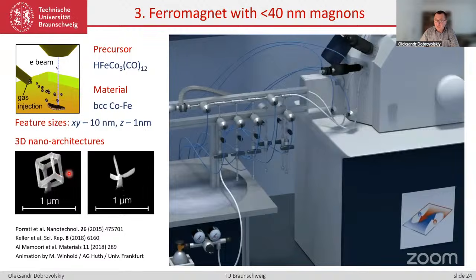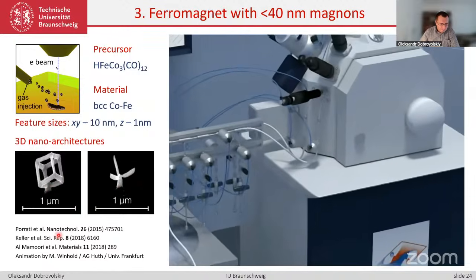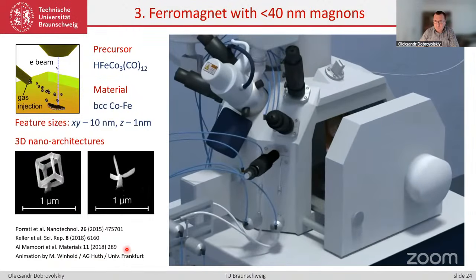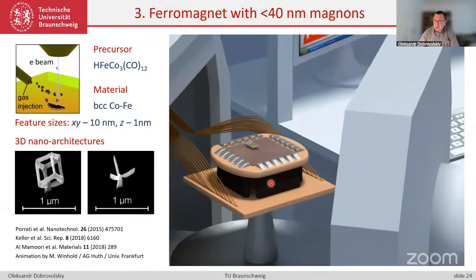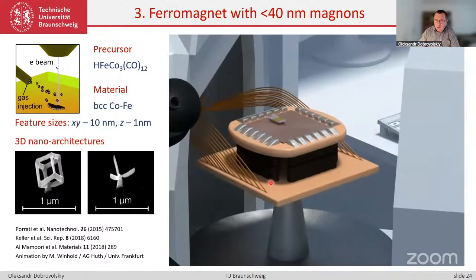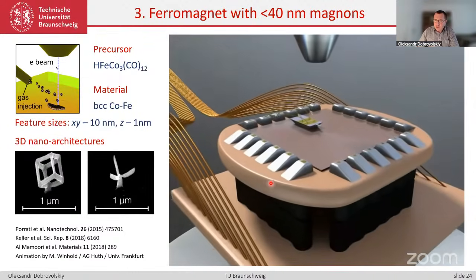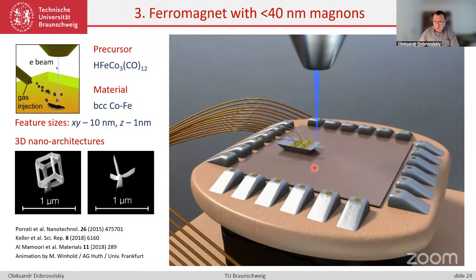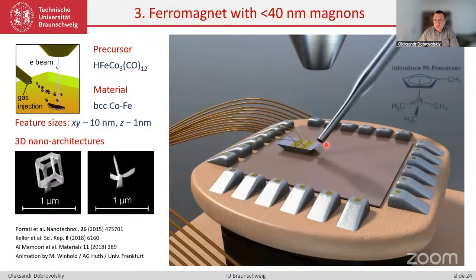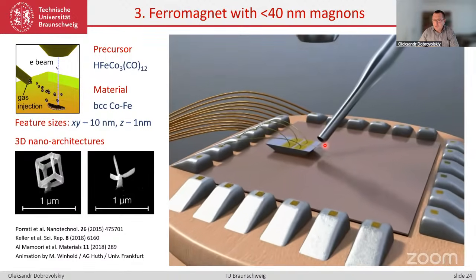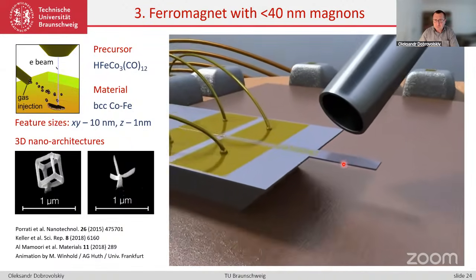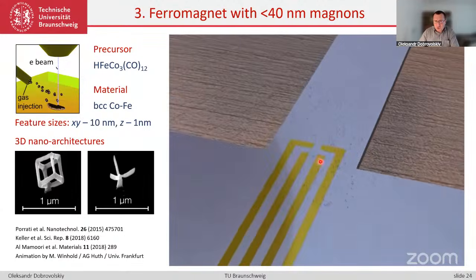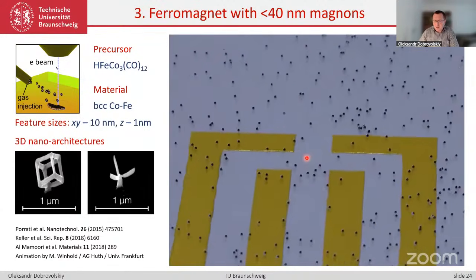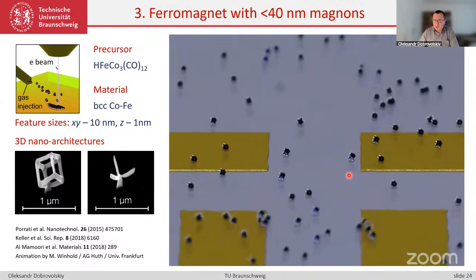They can also be what is shown here. These are three-dimensional individual building blocks, which we call nanotubes and nanotrees. And in these animations prepared by Marcin Winhold in the group of Michael Huth at the Goethe University of Frankfurt, this is just an idea of the process. A dual beam scanning electron microscope with a chip mounted onto it, where there will be a fabrication of a structure by means of focused electron beam induced deposition. Into the electron chamber, you see a gas injection system, which is introduced and used to let a precursor gas into the microscope chamber. Then, under optimal conditions, by thermal diffusion, these molecules of precursor gas are delivered to the vicinity of the area where the sample is going to be fabricated.